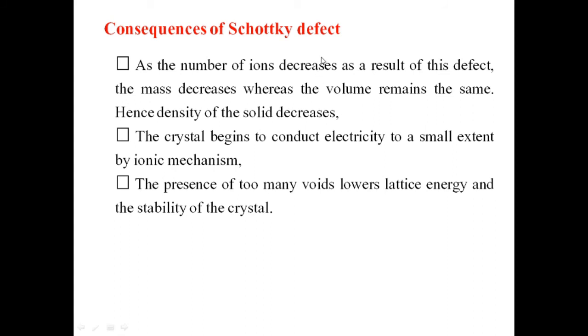Consequences of Schottky defect: as the number of ions decreases as a result of this defect, the mass decreases, whereas the volume remains the same. Hence, the density of the solid decreases in Schottky defect. The crystal begins to conduct electricity to a small extent by ionic mechanism. The presence of too many voids lowers lattice energy and the stability of the crystal.